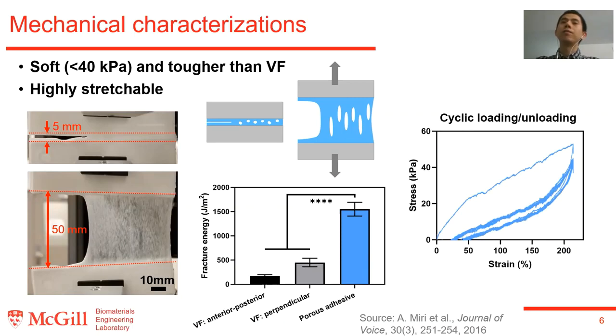It is significantly softer compared to the sutures and the cyanoacrylate adhesives. Because this measurement is conducted at 25% liquid filling ratio, which means it still has plenty of room to absorb the tissue fluid, we expect this stiffness to be even lower when the porous adhesives are saturated with water, and we can further tune the stiffness by controlling the cross-linking density and polymer concentrations.